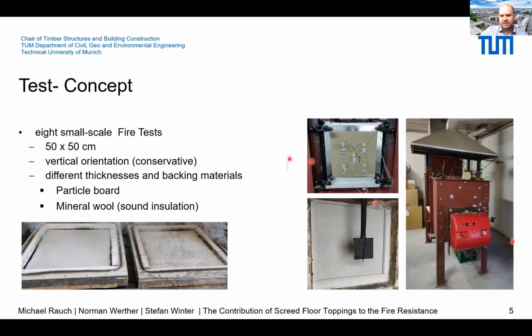The test specimens were mounted vertically because of the geometry of the furnace. This configuration is more conservative compared to the horizontal construction. To avoid the fall off, the screed layers were fixed by screws. Different thicknesses and backing materials, such as particle board or mineral wool insulation, were tested.